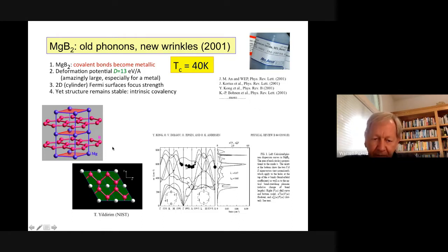It's a little bit more interesting because, unlike the BCS model with a single electron band, this has two distinct electron bands with different superconducting strengths. But otherwise, it's BCS-like. And what's unusual about it, and gets TC up to 40 Kelvin, the maximum TC in these kinds of materials having been 23 Kelvin since 1973, is this stretch mode of the bond that's extremely strongly coupled to the electron bonding state, that involves the borons here also.